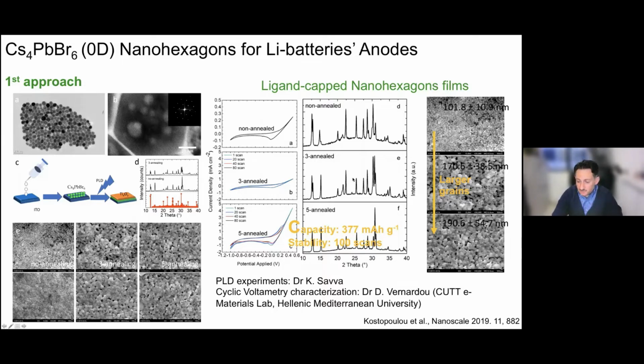We published this back in 2019. The second system is the ligand-free microcubes via direct growth. You can see again the current density versus potential characteristics, and in this case the capacity can reach up to 549 milliampere-hours per gram. The stability is much more improved in this case. This cell can last up to 1,500 scans.